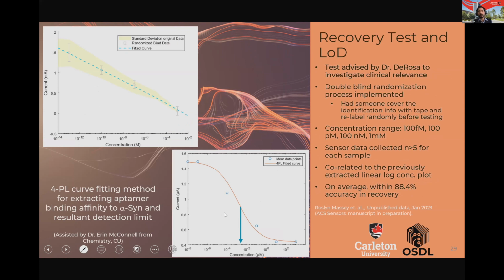and her colleagues, to show the clinical relevance, the viability, we did recovery experiments, which is to say that we extracted calibration plots from multiple device testing. We collected anonymized saliva samples, which were spiked with different concentrations of alpha-syn. And then we tested them and tried to predict their concentration. And as you can see, we were able to recover the alpha-syn concentration in an anonymized sample with very high accuracy, close to 90%.